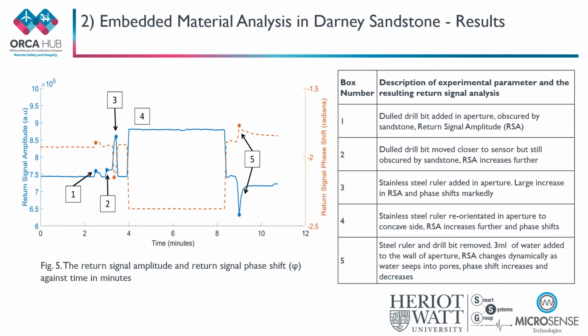At point 5, 3 milliliters of water is sprayed on the wall of the aperture using a dropper and allowed to dry at room temperature. From this result, we can identify that the return signal amplitude and phase each shift dynamically and is due to the water seeping into the pores of the sandstone and evaporating at room temperature.